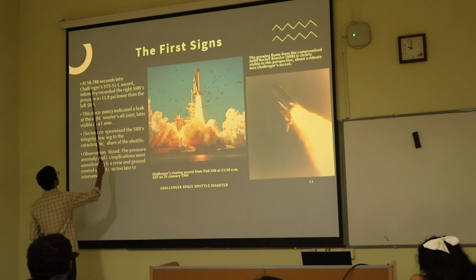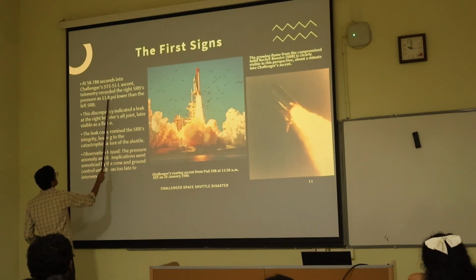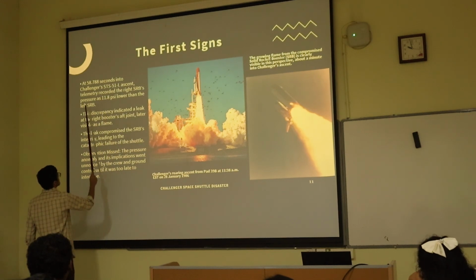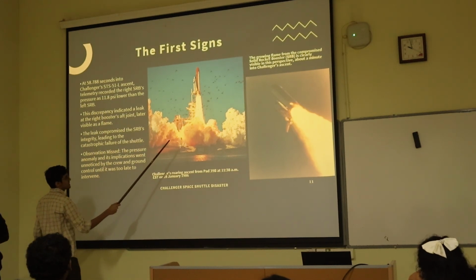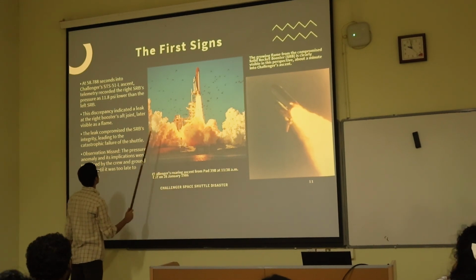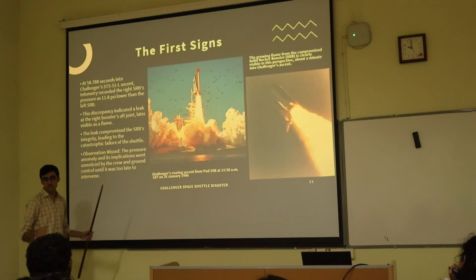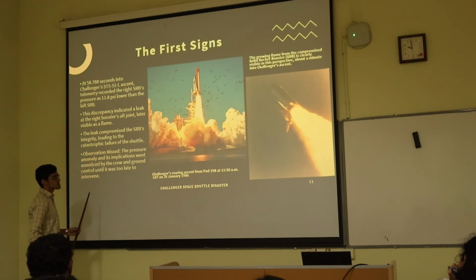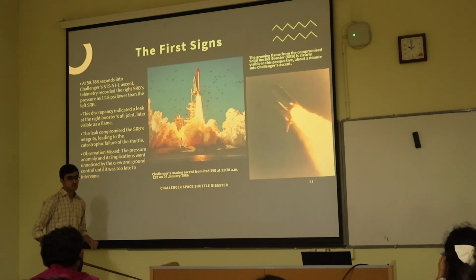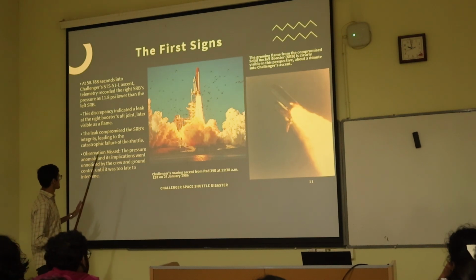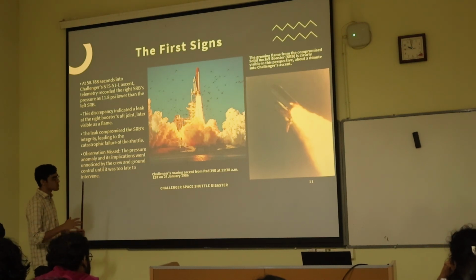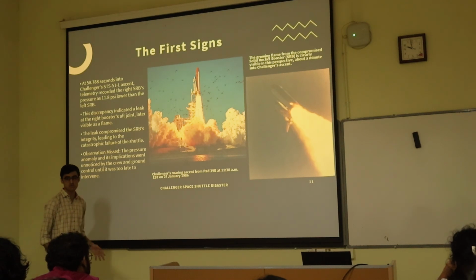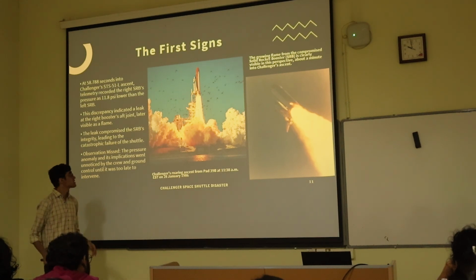But when this time occurred, the pressure was significantly lower compared to the liftoff. So this discrepancy indicated that there was a leak at the right SRB, and what this meant was that it totally compromised the SRB's integrity, and we saw that due to the pressure anomaly, nobody noticed how this went off and then the whole thing blew off.